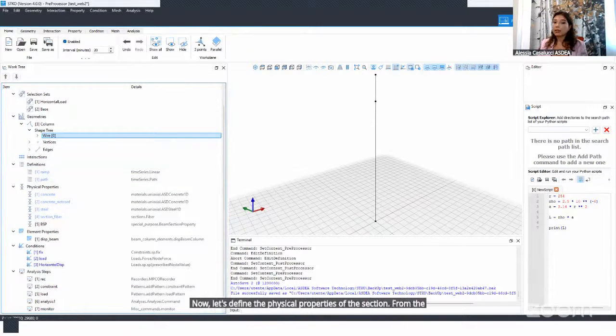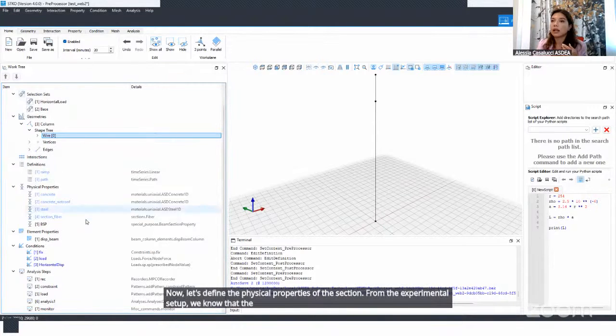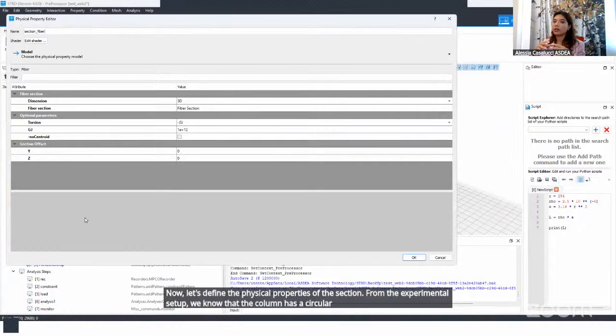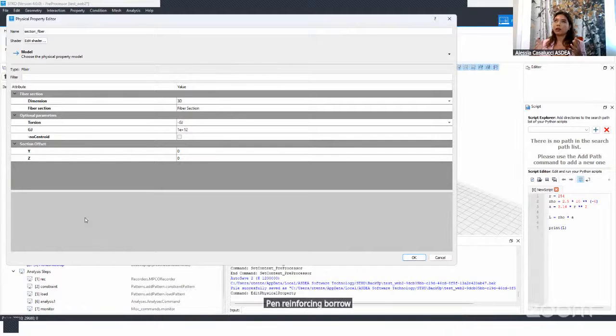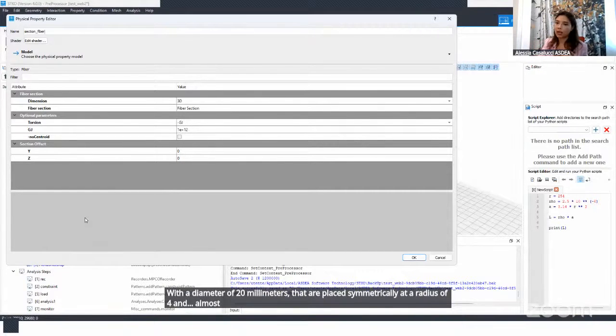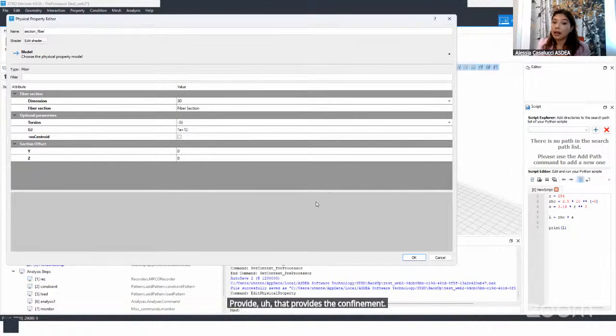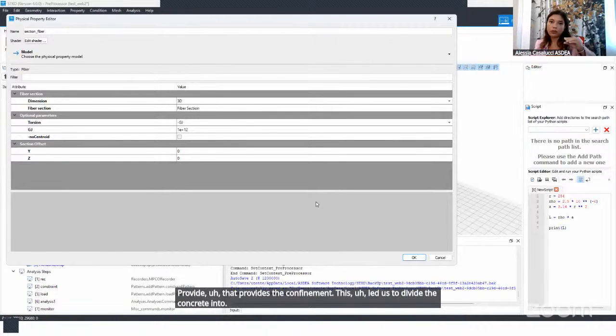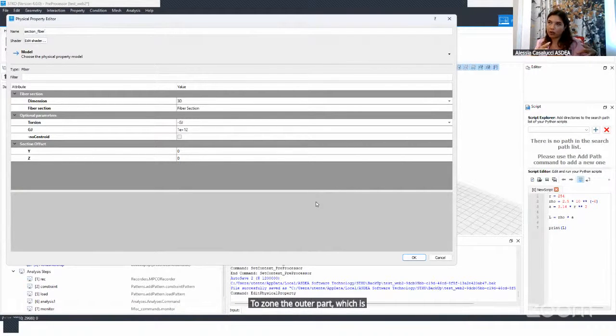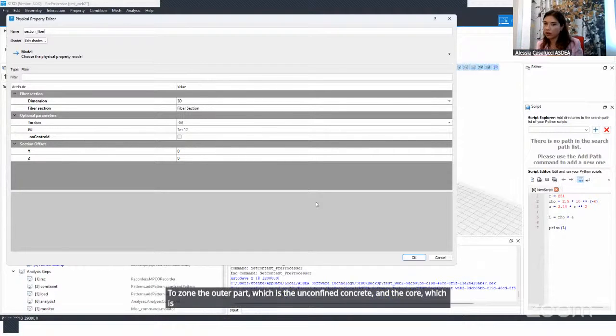Now let's define the physical properties of the section. From the experimental setup, we know that the column has a circular cross-section with a radius of almost 500 millimeters, 10 reinforcing bars, each with a diameter of 20 millimeters, placed symmetrically at a radius of 418 millimeters, and a continuous spiral stirrup that provides the confinement. This led us to divide the concrete into two zones: the outer part, which is the unconfined concrete, and the core, which is the confined concrete, due to the lateral pressure exerted by the spiral.